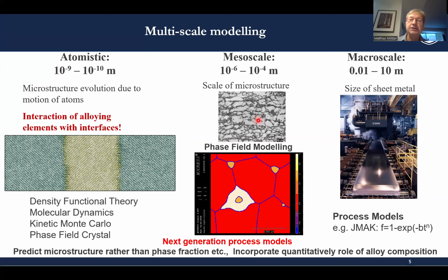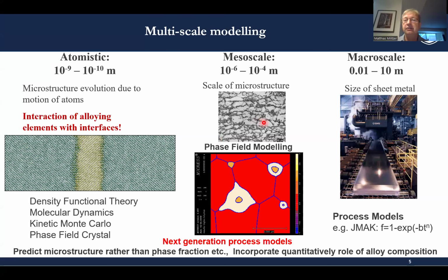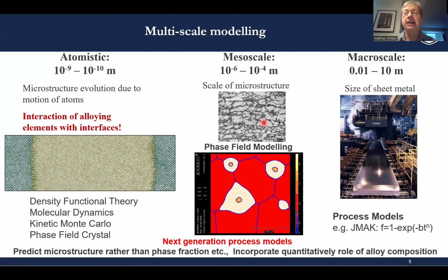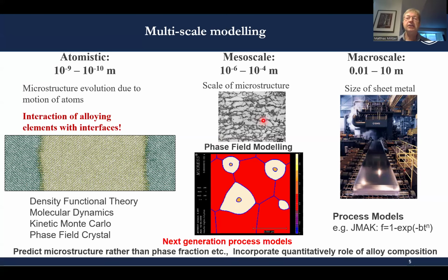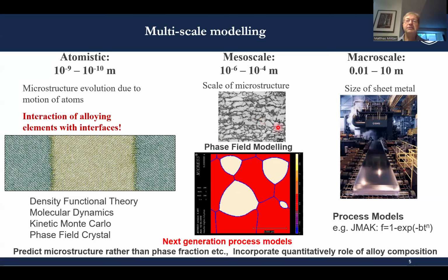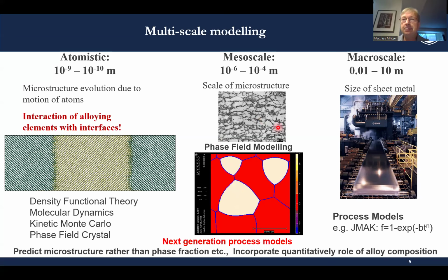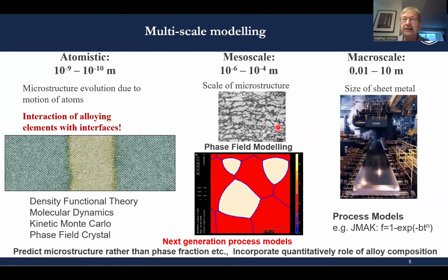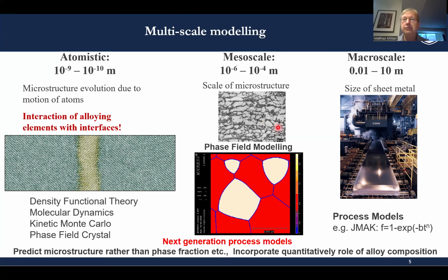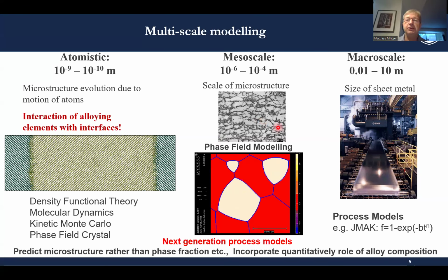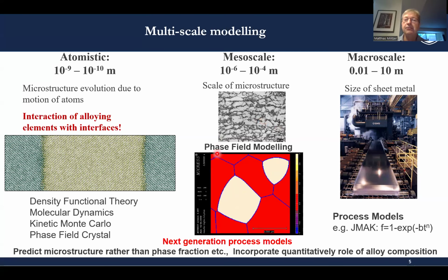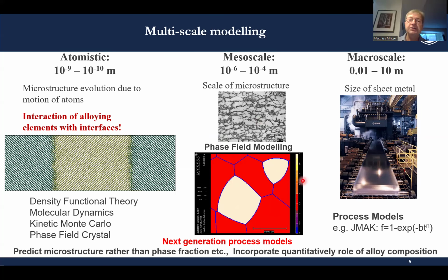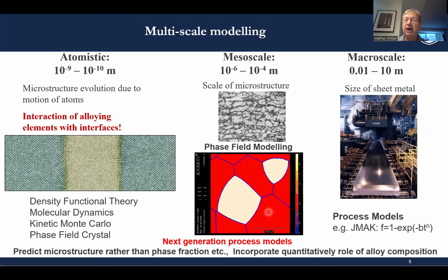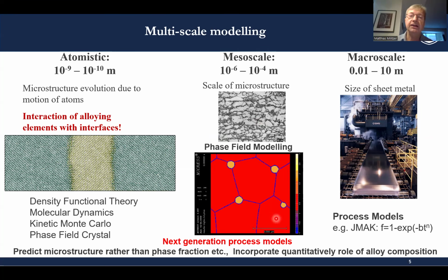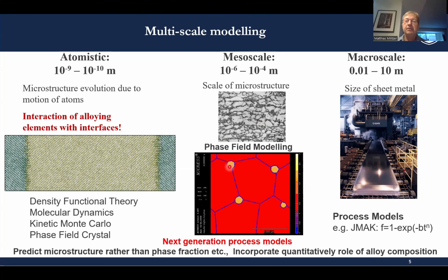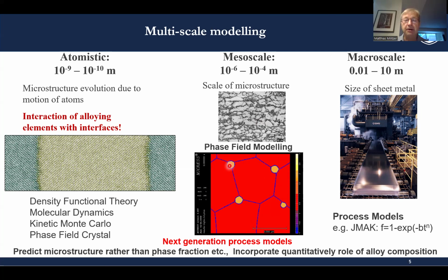For these sorts of steels, it's intercritical annealing in a continuous annealing line or hot dip galvanizing line that is a critical processing step, where we see the formation of austenite from a ferrite-pearlite or ferrite-carbide microstructure. And what is running here in the background is a phase field simulation of this intercritical austenite formation. So the white areas are austenite, red is ferrite, and these orange particles are carbides.